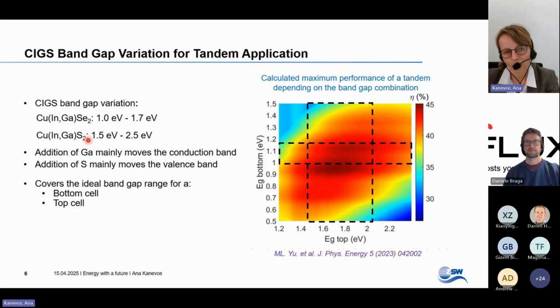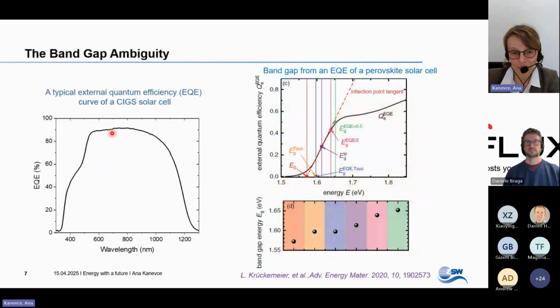Now, I mentioned when we want to modify our cell that we optimized for a single cell structure for a bottom partner in a tandem, the first thing we need to do is to adjust the band gap. But do we know what the band gap is? You know, our textbooks say, okay, this is something from external quantum efficiency and it drops off vertically at high wavelength range, and this is our band gap. But our quantum efficiency curves all have a slope. So what is the band gap here?